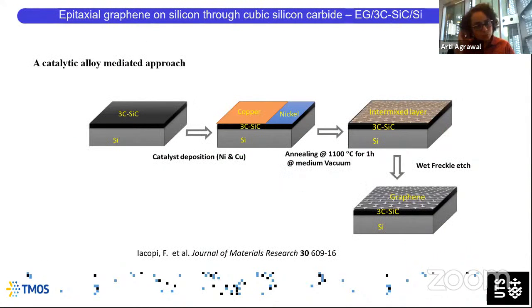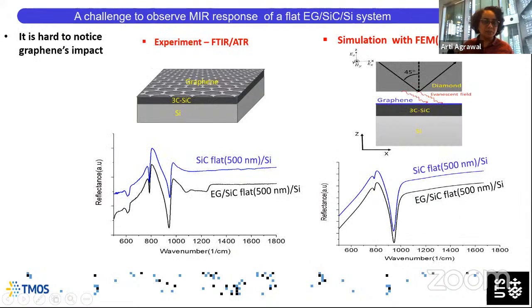Now, this is showing you a schematic of how we are creating this kind of a structure. This is using a catalytic alloy mediated approach. The end result is to get a thin sheet of graphene, about a bilayer or a single layer, on top of 3C silicon carbide, which is sitting on a silicon substrate. This is for a planar surface, but we can, of course, do things for non-planar surfaces as well. Before I go to the non-planar surface, I just want to share some results here with you.